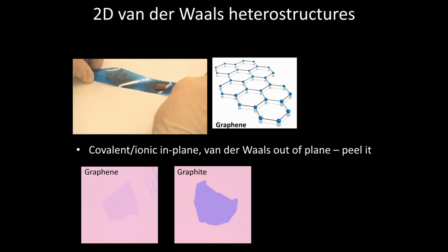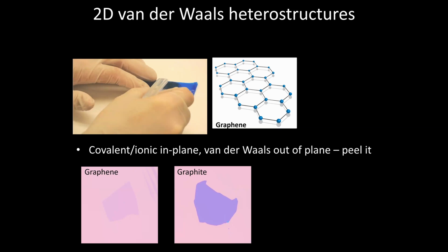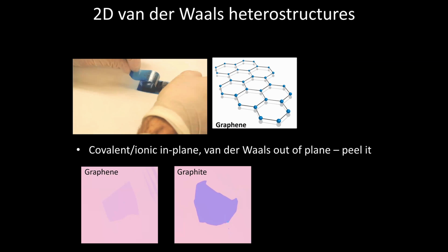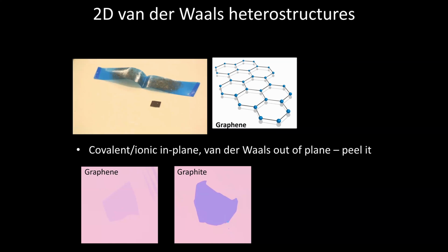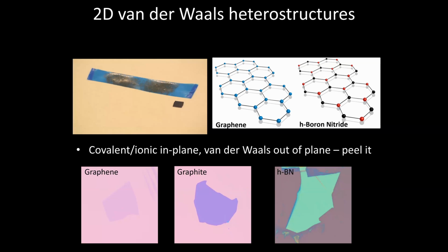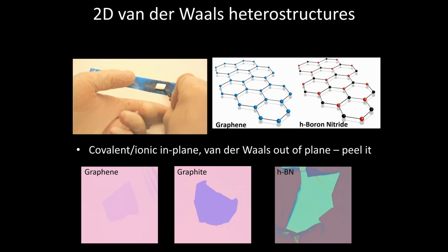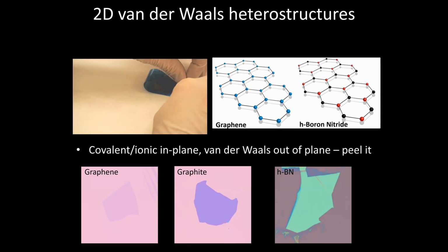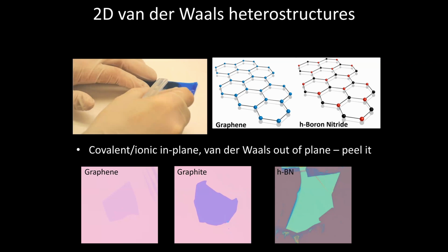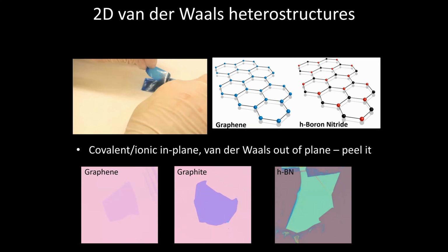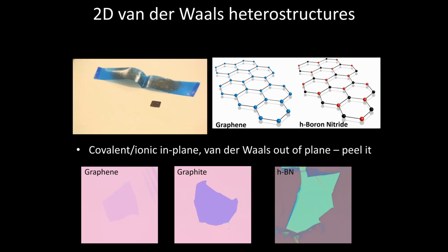This is what a monolayer looks like. This is what multi-layers look like. And you can basically spread these on a substrate and identify them, and that's your two-dimensional electron system that you're going to work with. Now, the important thing is that you are not confined to just studying a piece of graphene. You can turn these into heterostructures, and you do that by combining them with insulating or semiconducting or other metallic two-dimensional electron systems. And the most important of these is something called hexagonal boron nitride.